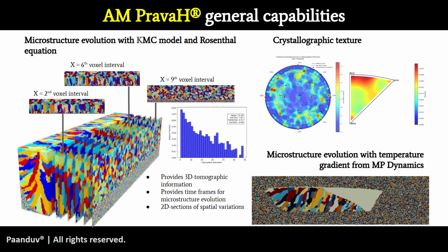So everything that we saw on the previous slide, those defects were captured using melt pool dynamics alone. But then there's a solidification aspect as well associated to additive manufacturing processes. And that's where microstructure evolution, how your grains are orienting, reorienting, or misoriented based on the movement of the laser over a particular alloy, is very critical. You want to look at the crystallographic texture, you want to look at inverse pole figures.